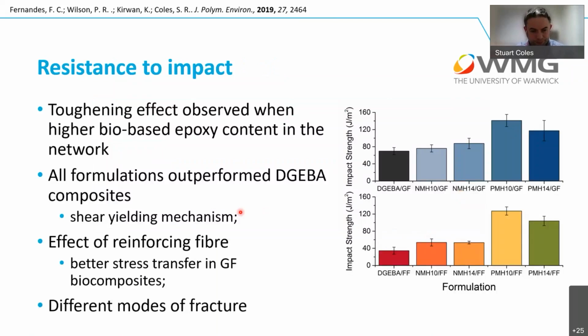And so we did a number of different formulations, again looking at the resistance to impact, and all of the formulations that we put together with various different glass fibers and flax fibers and different ratios of vegetable oil and hardener, all produced better material. It was effectively the reinforcing fiber. We were getting better stress transfer within the glass fiber biocomposites. We were getting different modes of fracture. And we were also starting to think about whether we were getting different modes of energy transfer through the composite. Were these polymer chains effectively having the ability to move and being a little bit more flexible? Was that helping to absorb some of the extra energy?